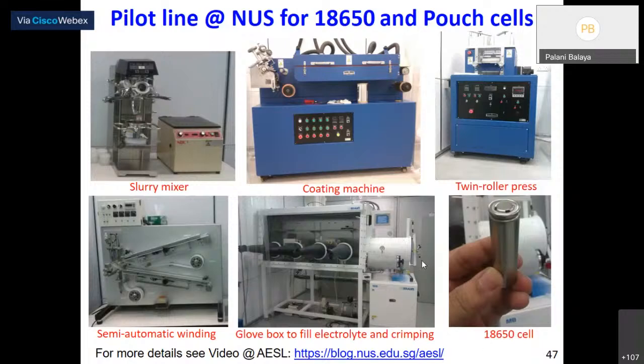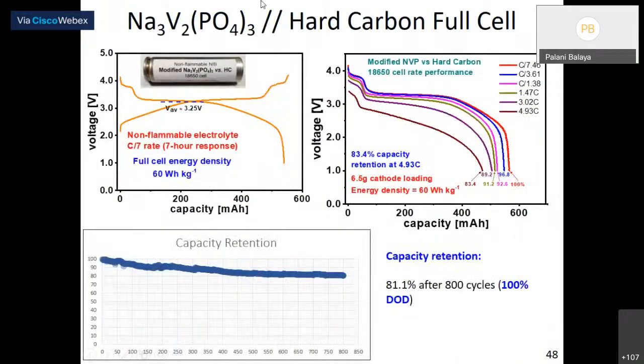So we have made this type of commercial type cells using sodium vanadium phosphate and hard carbon as the anode. You can see here, this is using pristine NVP versus hard carbon. This is using modified NVP, zinc doped NVP versus hard carbon. I think both of them are zinc doped. I'm sorry for that. So I'm not comparing pristine here because I don't have much time. This is the charge process. You can see here clearly there is a plateau, which is because of the vanadium 4 plus to 5 plus. This is the discharge profile.